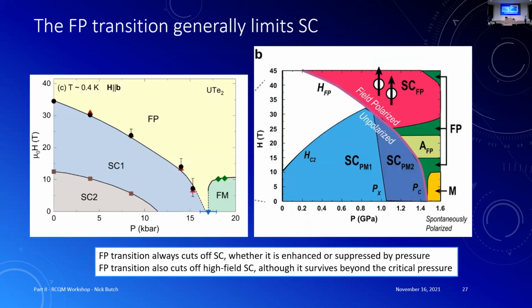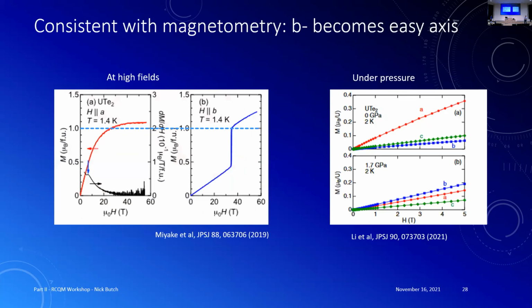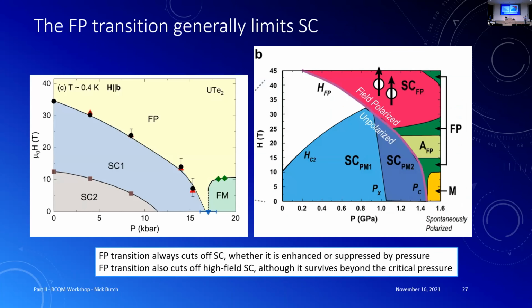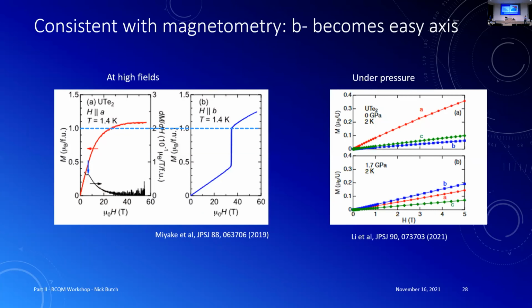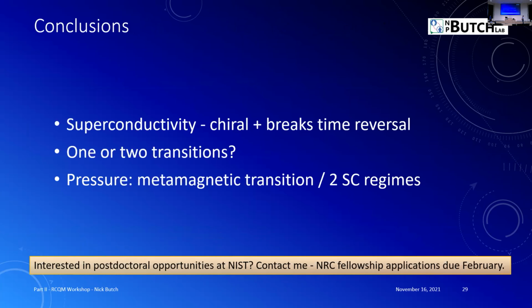Okay, and this is what the phase diagram looks like. So this phase actually extends out farther than the critical pressure. And I promised I would talk about the metamagnetic transition. So one thing that happens is that this is from a Japanese group, that the A axis and B axis magnetization switch at ambient pressure at that field, okay? So there's a step and then the magnetization of the B axis sort of takes over. Similarly under pressure, A and B switch. So I would argue it kind of has to happen because this phase boundary is falling, right? So it doesn't matter how you cross it. Eventually the B axis has to be the easy axis. Okay, that's it.